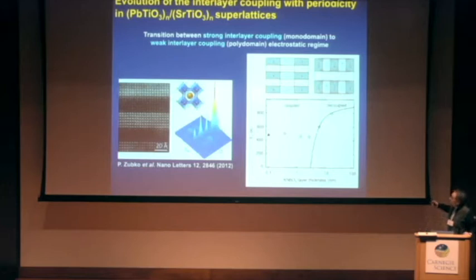So if we combine a ferroelectric and a dielectric material in one of these superlattices, any discontinuity in the out-of-plane component of the polarization at the interface between the ferroelectric and the dielectric may yield very large depolarizing fields that are energetically very costly. So one way to get rid of this electrostatic energy penalty is that